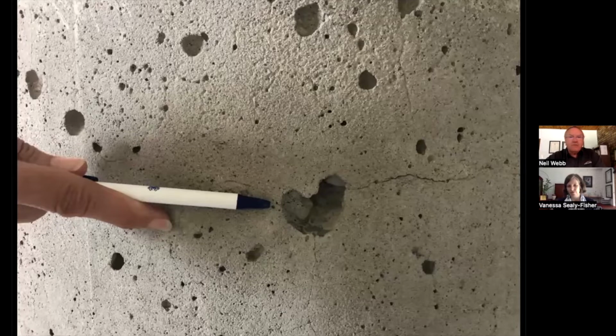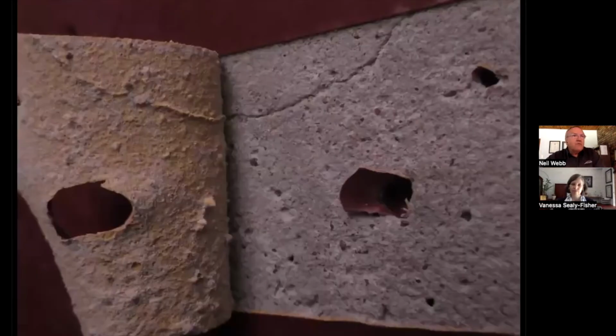You may well have seen people working on casting of concrete, and they have those high-pitched, very noisy vibrators that are used to endeavor to prevent the retention of air in the concrete. You can see micro cracks in the concrete, all of which are a challenge if you now want to coat this material. And here is a photograph of that same concrete surface where somebody attempted to apply a coating, and you can see that the coating has hardly even adhered to the underlying concrete.